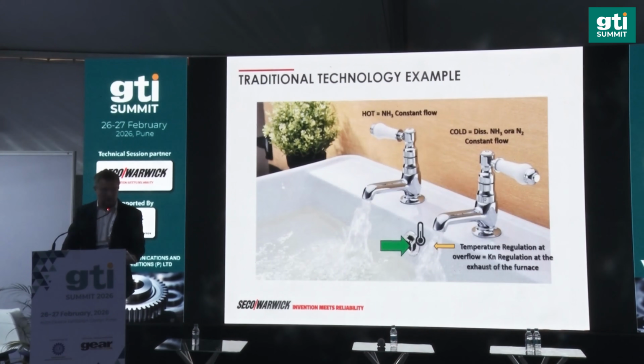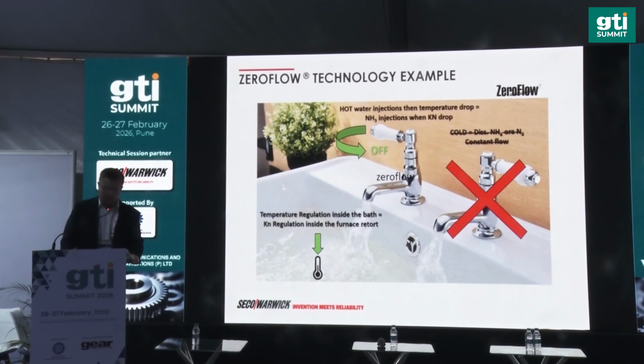In simple words, we can compare the traditional process to these two British taps. You know it very well, much better than me, I suppose. We have one extremely hot, which means ammonia, and the second one extremely cold, which means dissociated ammonia. For the traditional process, we fix the taps in some position just to get the right temperature. Temperature means nitriding potential, and in this example we can say it is like a bath temperature. So we are measuring the bath temperature in the drain, because all taps are open, so the flow is constantly going through the bath. In our technology, we are using only the hot tap.